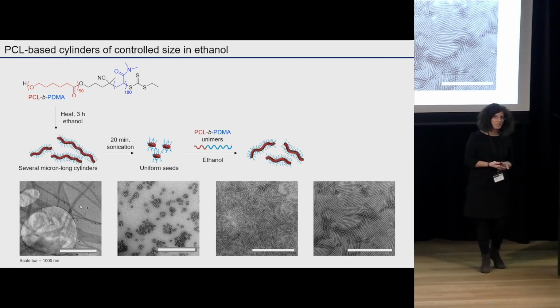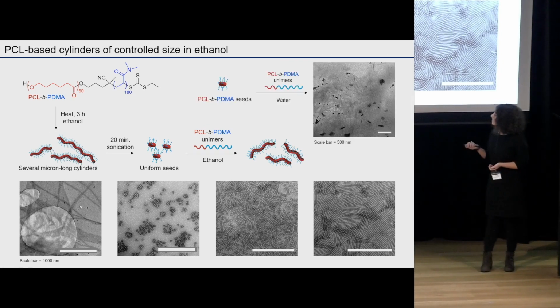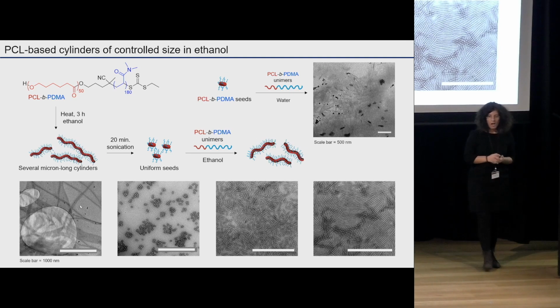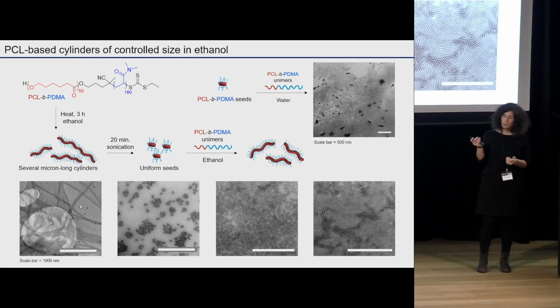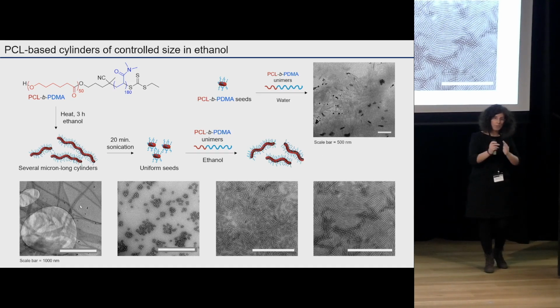But what I was really interested in is, can we actually do this in water so that we could use these nanoparticles for biological applications and to interface them with cells? However, no matter how hard we tried, the nanoparticles were crashing when I transferred them into water. That is because water was getting in contact with the polycaprolactone core, the red side of this polymer here, and by getting in contact with it, it was disrupting the crystallinity of our nanoparticle, and the nanoparticle was collapsing.